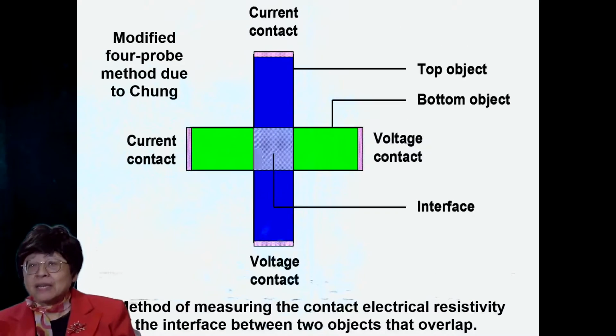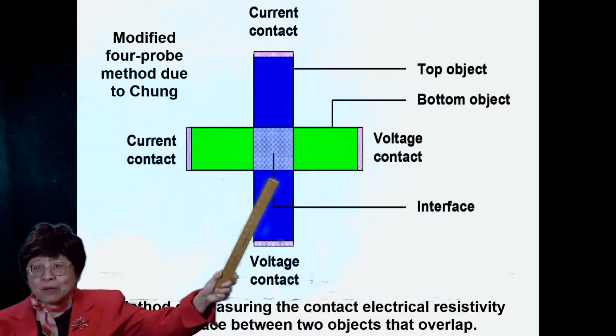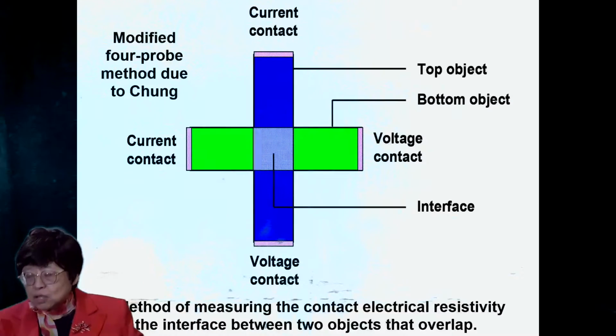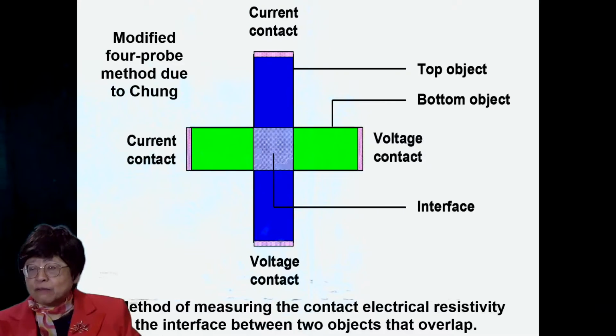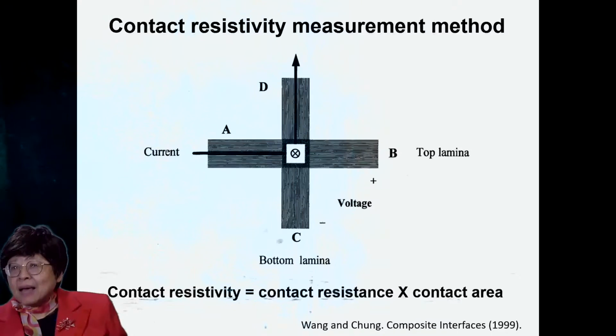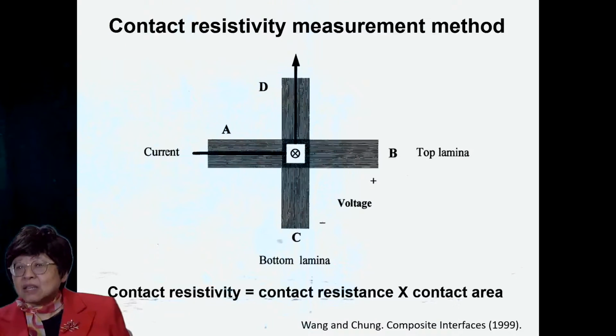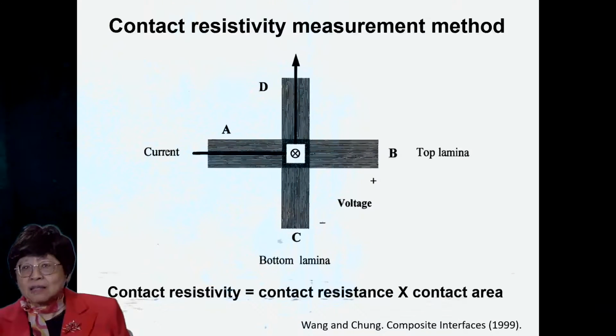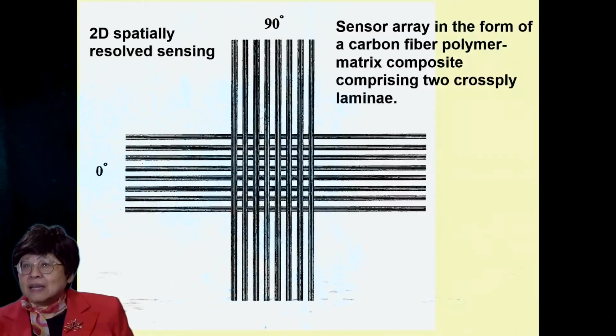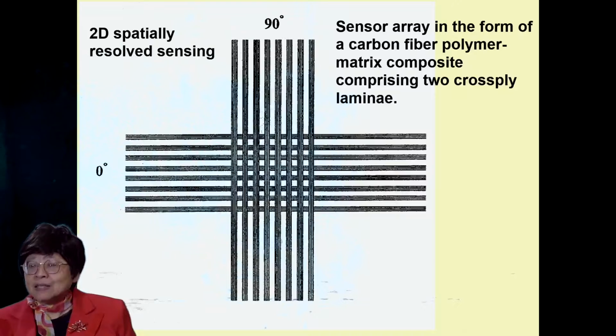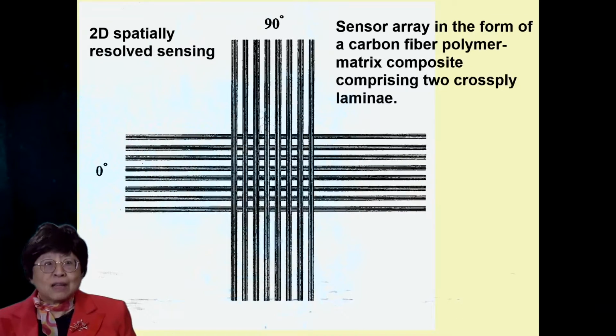We can measure the interlaminar contact resistivity by using this modified 4-probe method that I devised. I have two plies overlapping, and the overlap region is the interlaminar interface, and I have 4 legs sticking out to accommodate the 4 contacts for the 4-probe method. And so the contact resistivity is the contact resistance times the contact area, which is this overlap area. Another nice thing about this technique is that one can have a 2D array of interlaminar interfaces, and so a 2D array of sensors, thus resulting in 2D spatially resolved sensing.